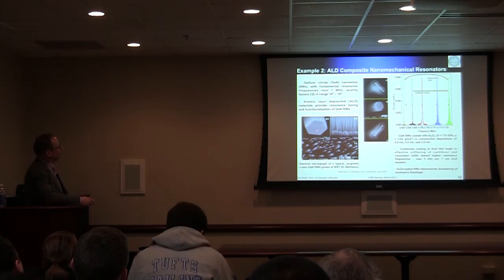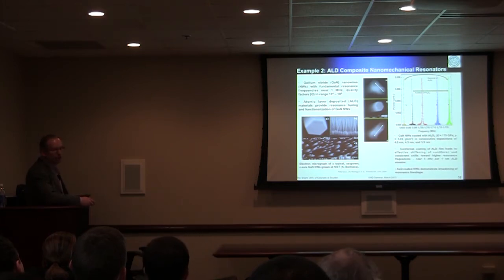So, just a few photographs here. Here's what these nanowires look like, typical structure for gallium nitride crystal. You get a forest of this type of nanowires. And here's an example of individual nanowire resonances. So this is the device without resonance, and then you can oscillate in this mode or this mode.